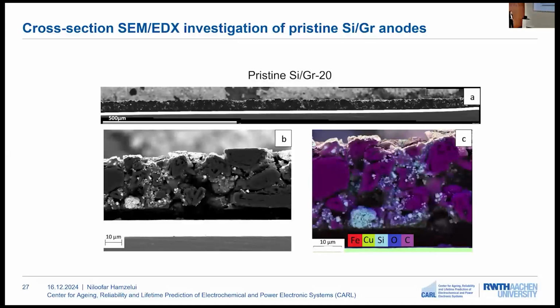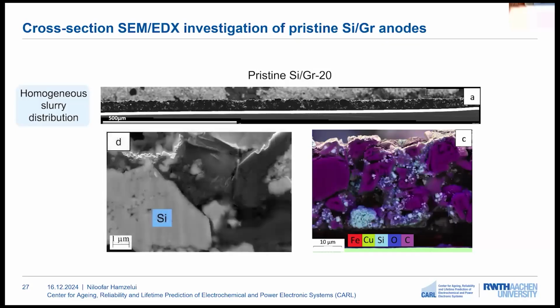Here we can see a cross-section SEM image of the pristine silicon graphite electrode with 20 weight% silicon. In the top image, we have a panoramic view of the electrode, and we can see that this film is homogeneously distributed on top of the copper current collector. If we further zoom in, we can better see the structure of the cell, and based on the EDX mapping, here we can see the distribution of graphite particles shown in purple and the silicon particles in blue. If we zoom in further, based on the EDX results, here is how a silicon particle structure looks before electrochemical cycling.